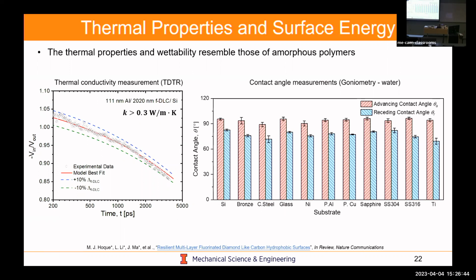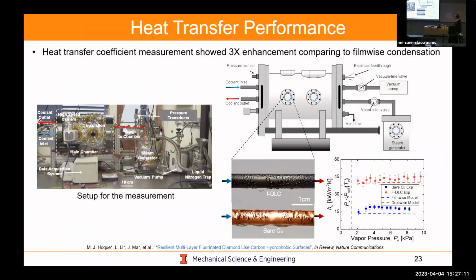If you measure the thermal conductivity of the DLC, it's about 0.3. So you're not gaining much over here. It's still fairly low, but you're mainly going to gain on the mechanical properties. And if you look at contact angle measurements, so this is using goniometry and water for multiple substrates, right? You're getting pretty good hydrophobicity, pretty low contact angle hysteresis. And so what I'm plotting here is advancing and receding contact angle, and these should be dropwise condensing. So I'm talking about dropwise condensation here. It's important to show you that this will actually work and give you an enhancement.